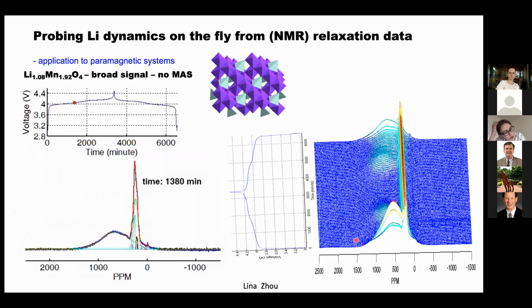I wanted to show you this one example, partly because I was talking to a material science department, where it's a nice illustration of how you can use these methods. So this is a result now for the spinel. I'm now on the cathode side, and this is a material where you've got manganese in the octahedral sites, and these are the lithiums that can go in and out. And you can oxidize this material at 4 volts, and there are 2 processes, one at about 4, one at 4.2 volts, and you can do NMR on it.